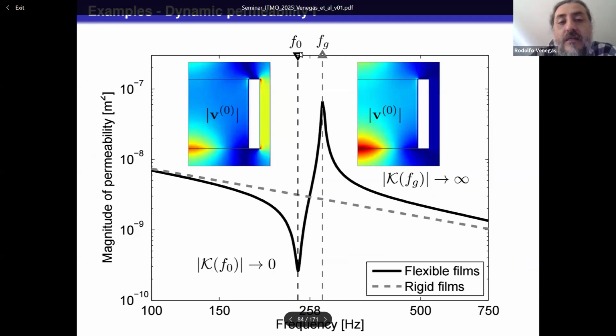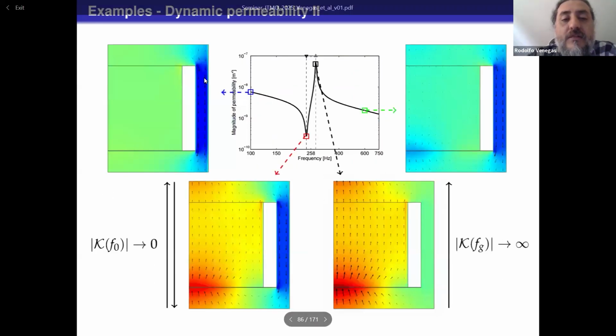But at a frequency F0, we have the anti-resonance. We have that the magnitude of the permeability is very small, while at the resonance frequency it is much higher. And then at higher frequencies, it will tend to the classical case, but this pattern will repeat.